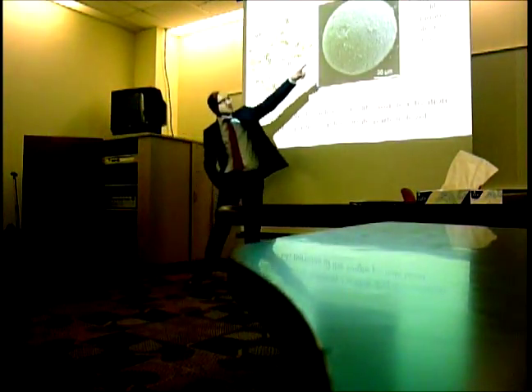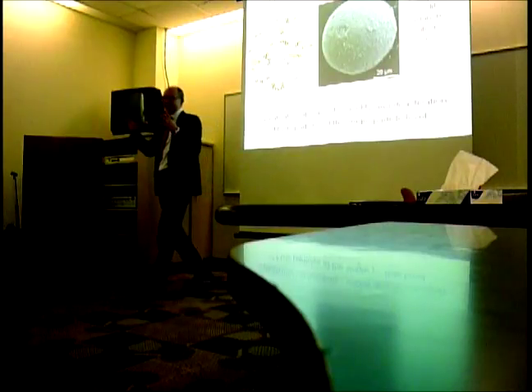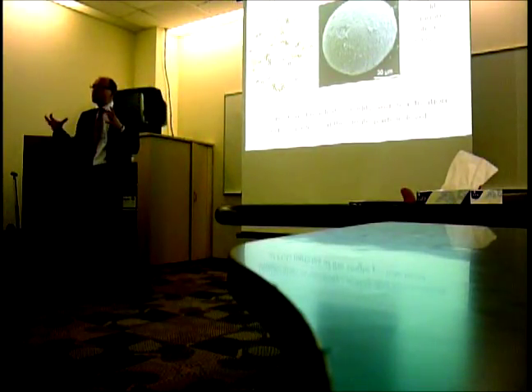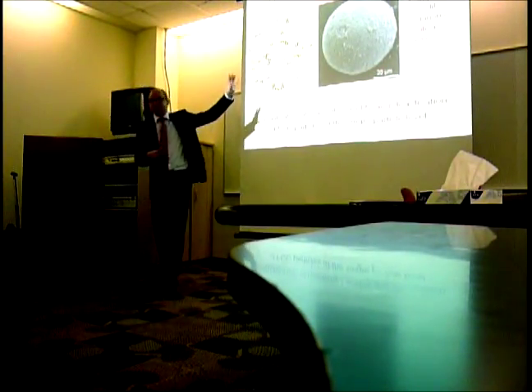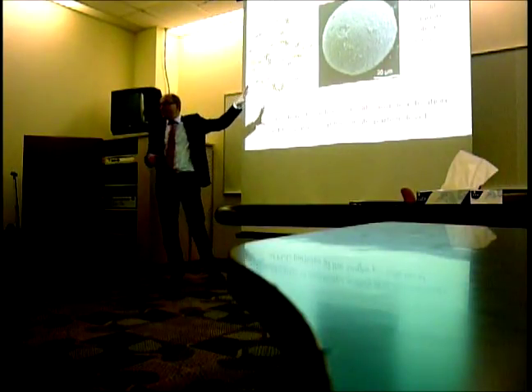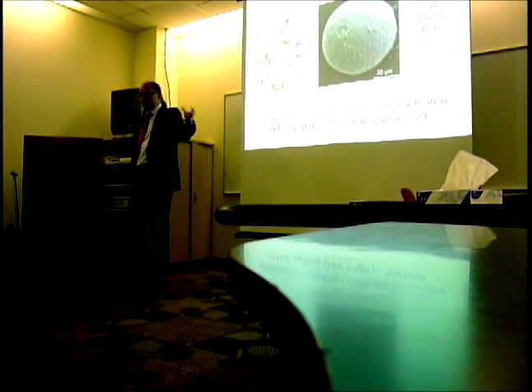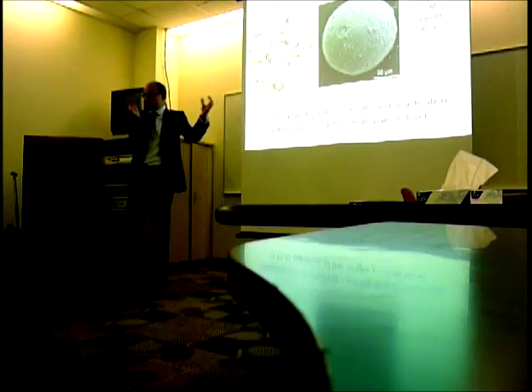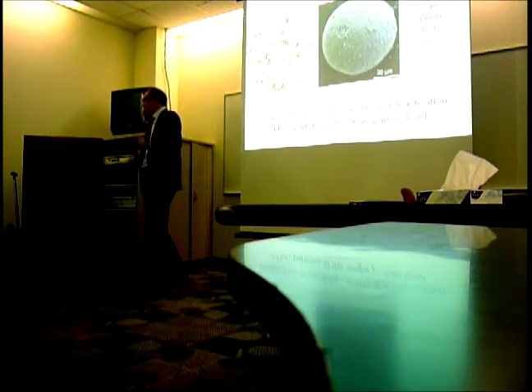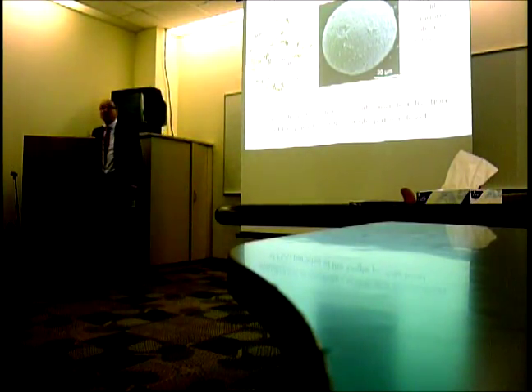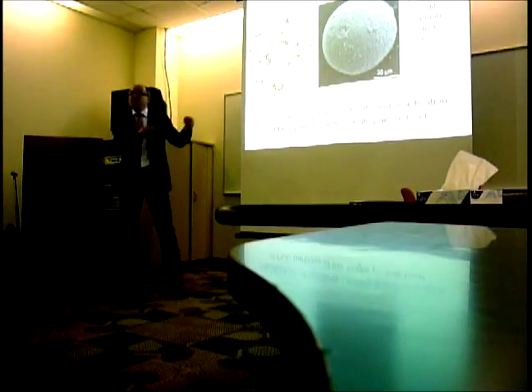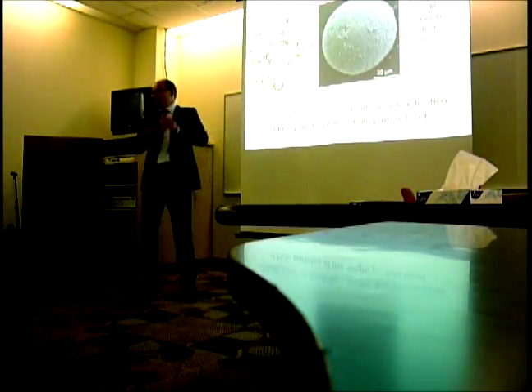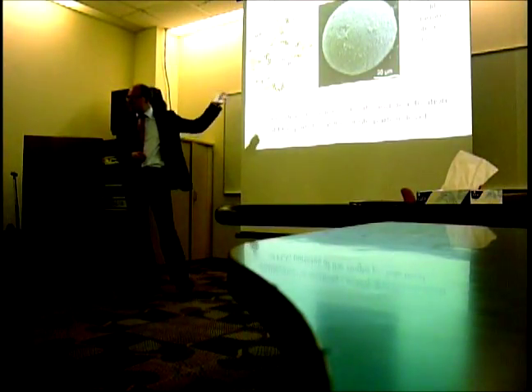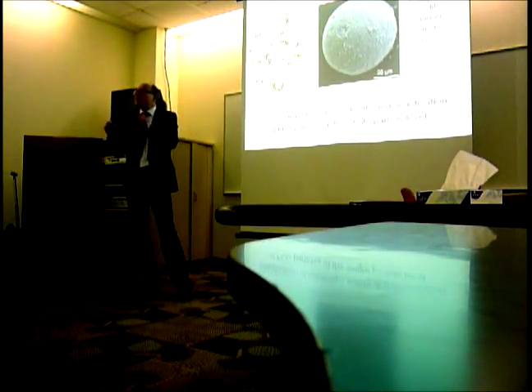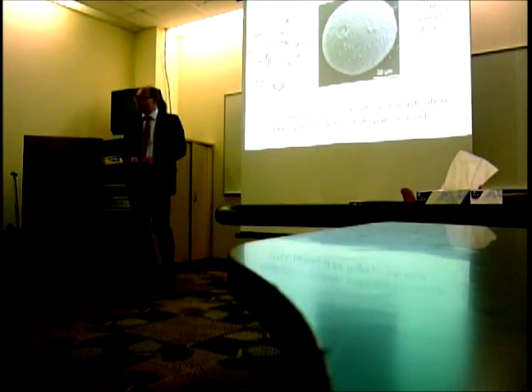These are balls of about 70 micrometers. And they are not uniform, they contain zeolites, these crystals I showed you before, but a bit smaller, together with a lot of other material. So now, I showed you that we can stain catalyst. Can we now stain this industrial material, and show where the zeolite is, where the active component is?